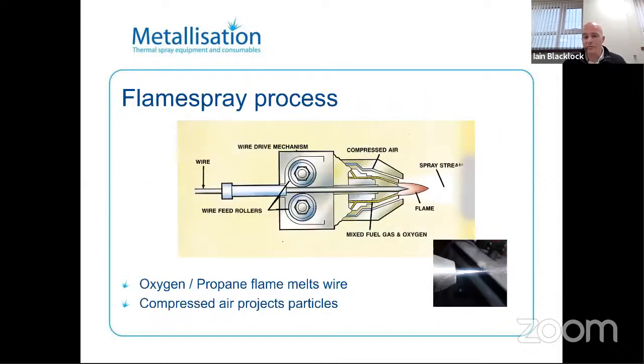So the process is to apply zinc, flame spray. What we do, we have either oxygen acetylene or oxygen propane. We create a flame on the front of the pistol. We bring the coating wire through into the flame. The flame will melt the wire. Compressed air will atomize and create the molten particles, and this is then propelled onto the substrate material. You can see on this illustration here, the arrowhead here is the coating wire, and you can see, hopefully, just the little molten particles coming off the front end, which have been atomized off the front end of the molten wire.